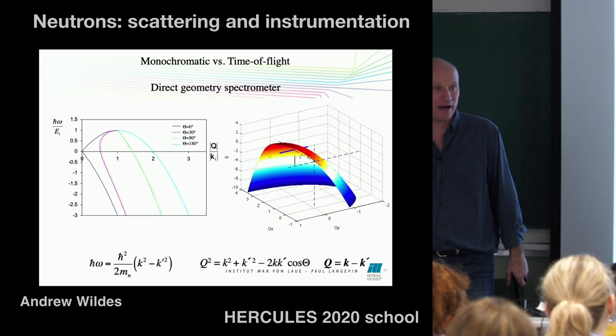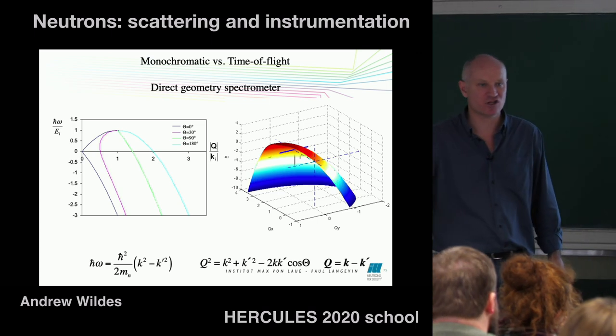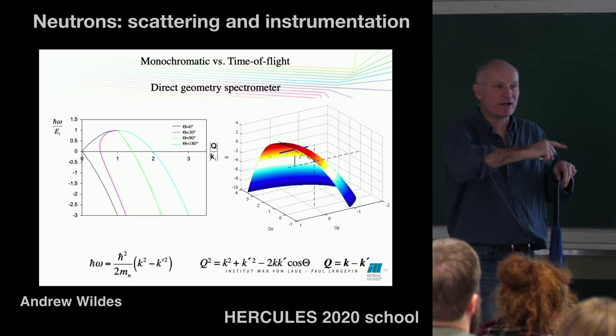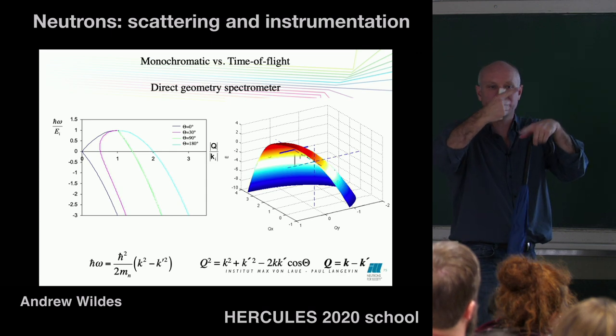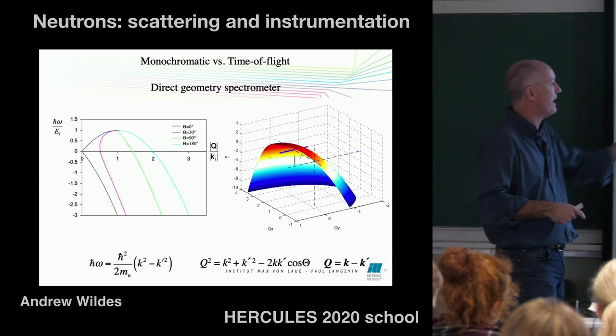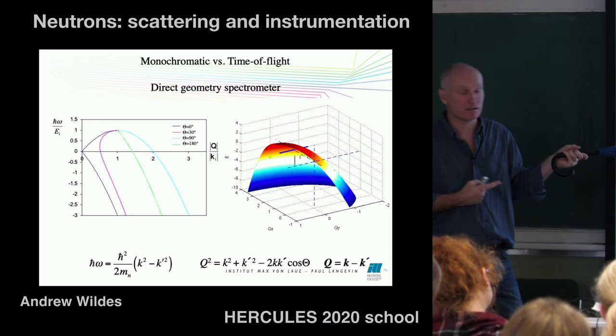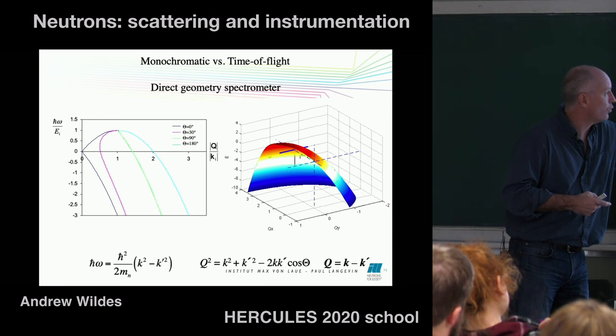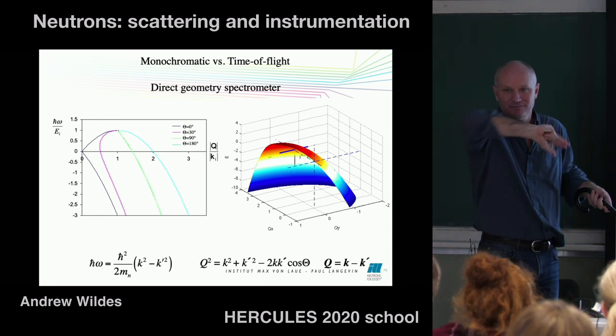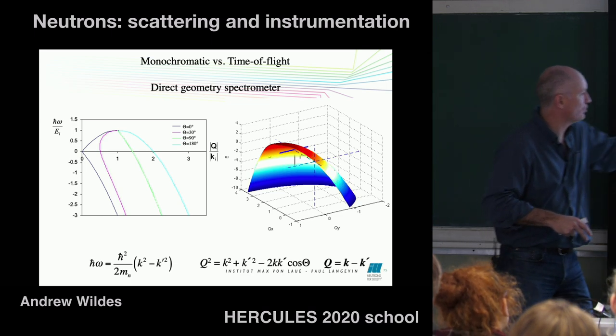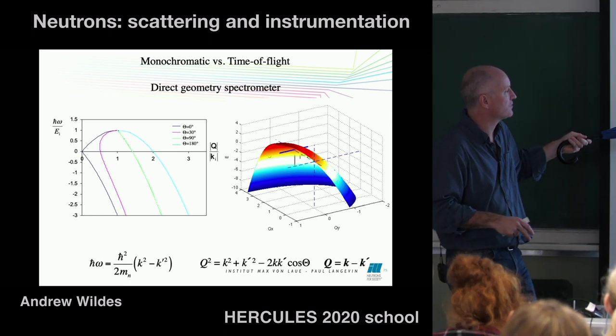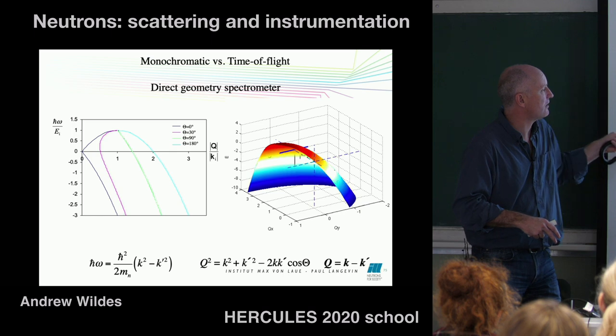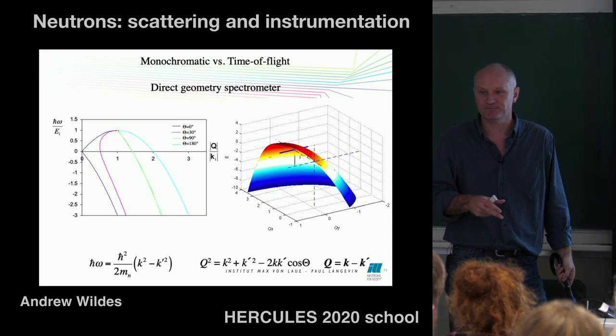Now, if you're doing this on a powdered sample, you don't really care about the direction of the vector. You lose all directional information in a powder. It's all randomly oriented. So if you had some powdered sample, and you'll often see pictures that look like this, you'll see your Q omega map, if you like. It's magnitude of Q. And this is the energy transfer. It'll look something like this, and your scattering will be somewhere in a shape that looks a bit like that.